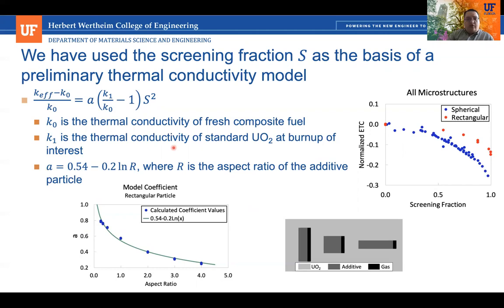So essentially the case where we have the same amount of irradiation and damage with no additive at all. We're assuming that over the whole microstructure, we're going to sort of average out those worst case scenarios where it actually gets a little worse. And then we have to come up with some way of representing the change in the geometry.